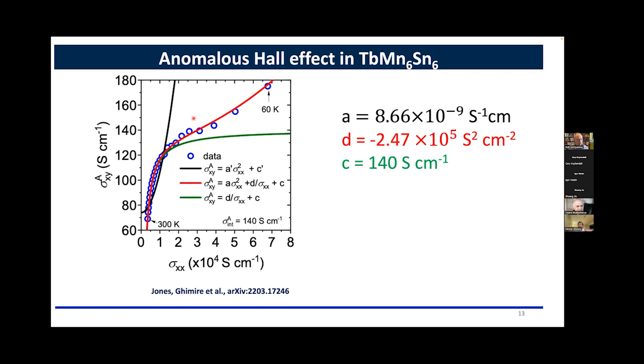And empirically, we tried different things to fit this data. What we found, interestingly, is that as soon as we add this 1 over sigma XX term to this data, it fits perfectly. It not only fits, but it gives rise to a similar value of this intrinsic contribution as if we were not using this 1 over sigma XX term.